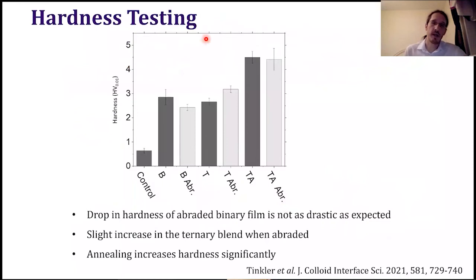We also tried to assess the hardness, but I think this wasn't the best type of test because the hardness indenter goes quite deep into the film. The film is not super thick, so I think it's testing more the whole film rather than just the surface or just the top layer.